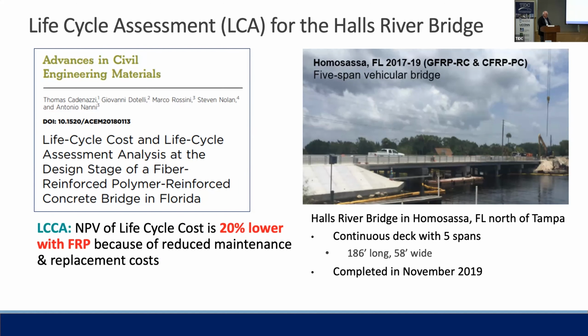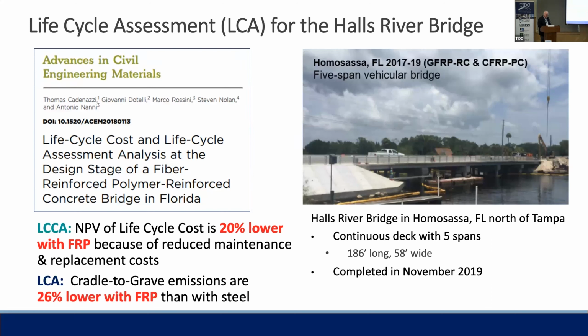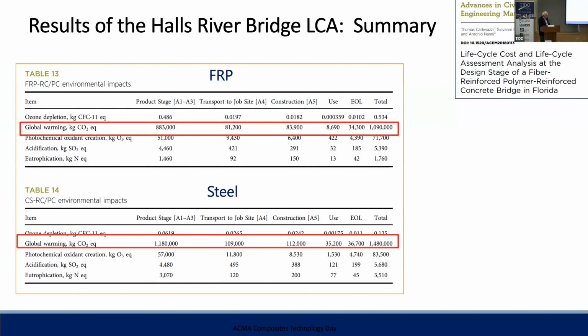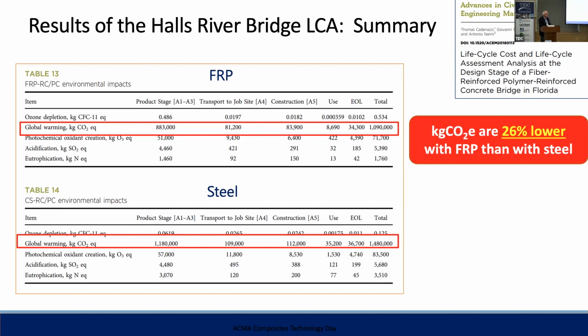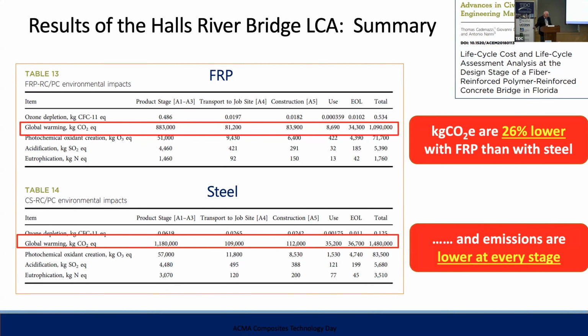Their LCCA showed that the net present value of the life cycle cost is 20% lower with FRP because of reduced maintenance and replacement costs. That's a good story for FRP. That's a story for a different day. Relevant today is that their LCA showed that cradle-to-grave emissions were 26% lower with FRP than with steel. And here's the data that shows that. The table at the top contains the emissions data in kilograms of CO2 equivalents for the bridge with FRP elements versus the one with steel elements. And if you compare this data point with this data point, you will see that the emissions are 26% lower with FRP than with steel. And they are lower at every stage in the process.